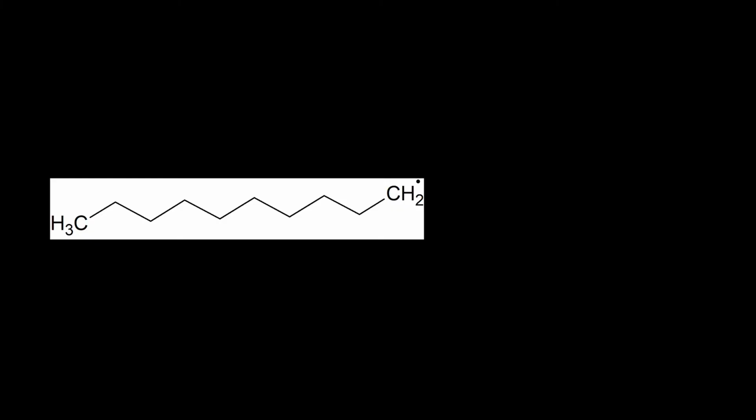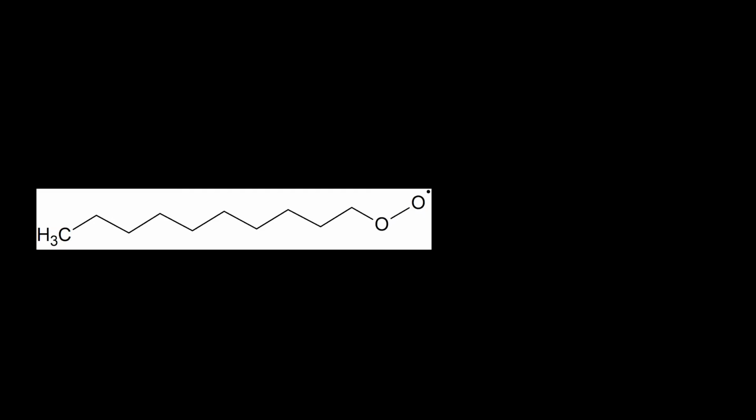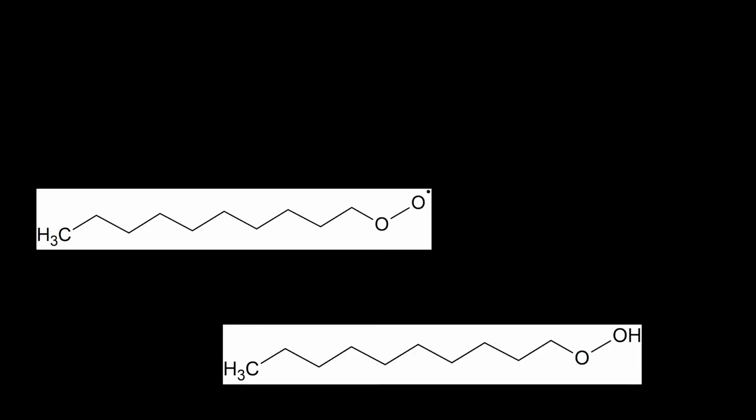The radicals are incredibly sensitive to side reactions, and this brings us to the major obstacle of photopolymerization and one of the core ingredients to CLIP. As you might have noticed, our atmosphere contains oxygen. This can diffuse into the solution and react with the radicals. This in turn forms peroxy radicals that, through hydrogen abstraction from solvent molecules, form hydroperoxy terminated chains.